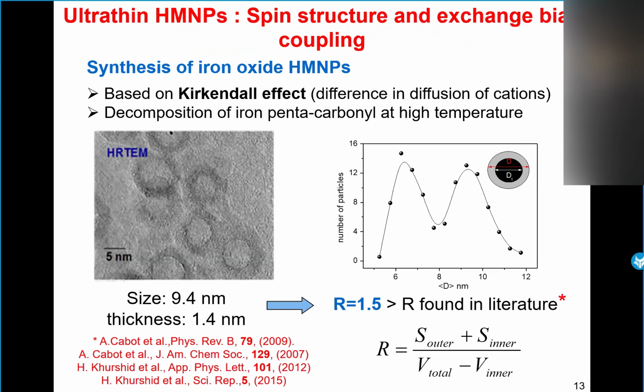So the obtained hollow magnetite nanoparticles are characterized by a very small thickness. And if we compare the surface to volume ratio, we found that R is bigger than the R found in literature. So we have a lot of surface in this system.